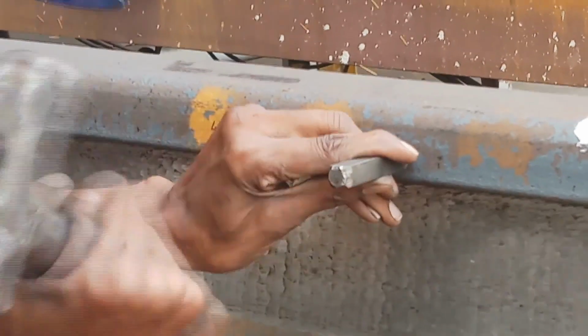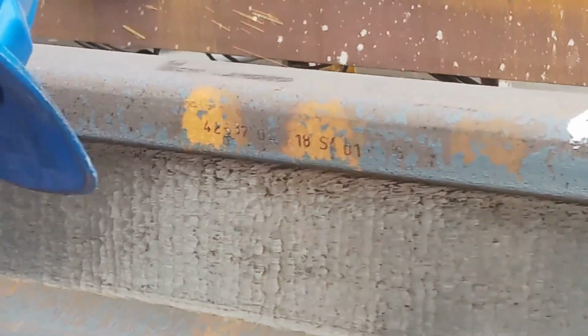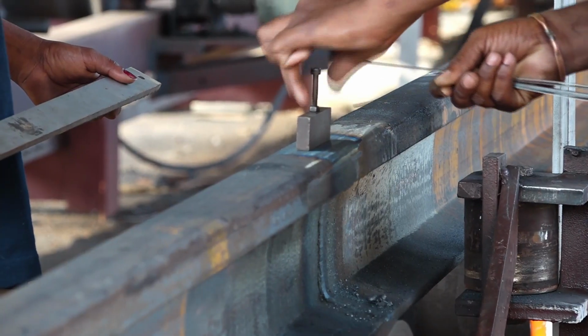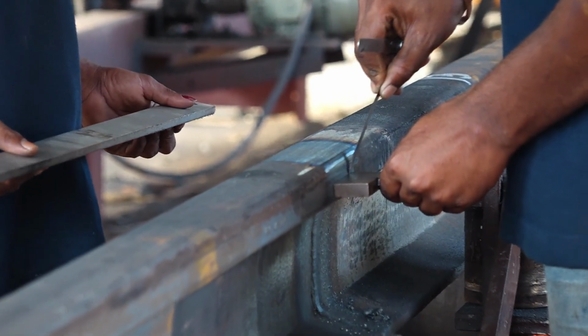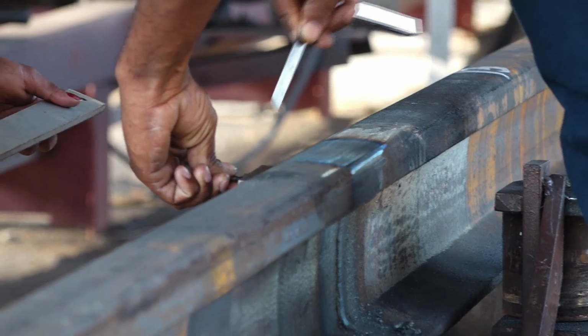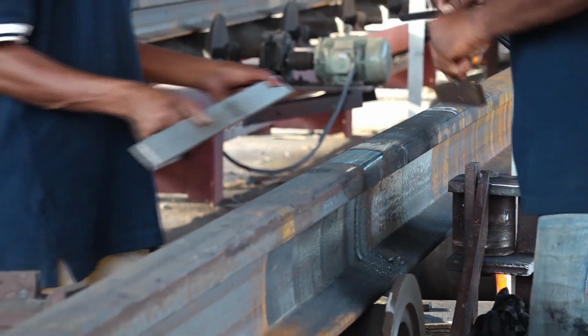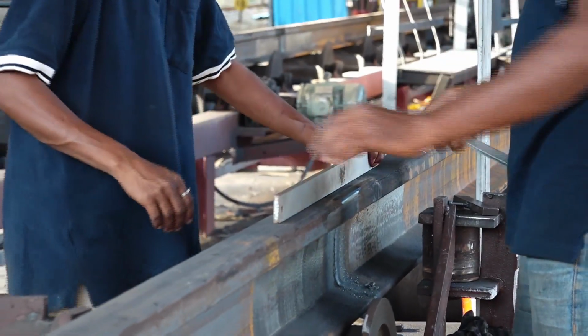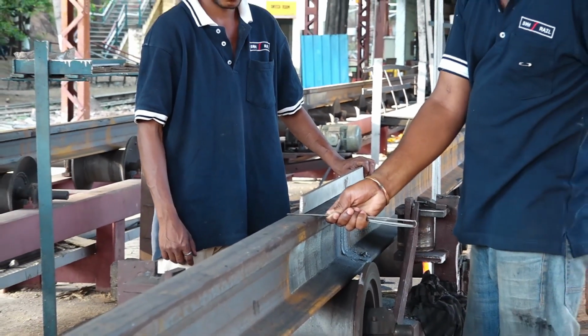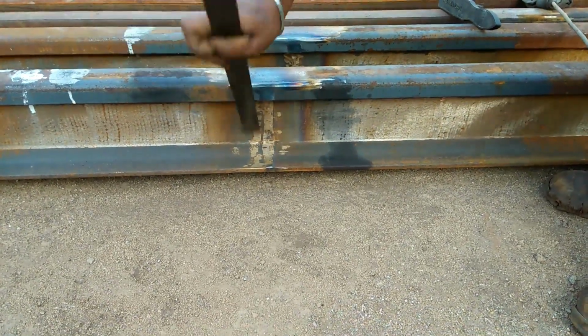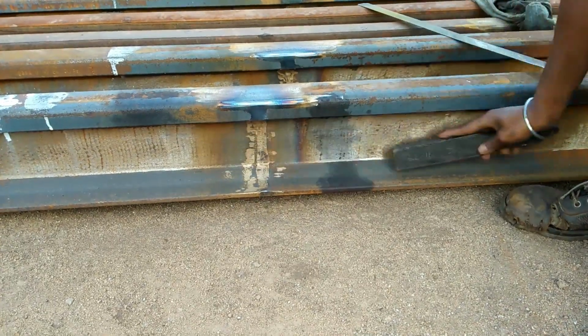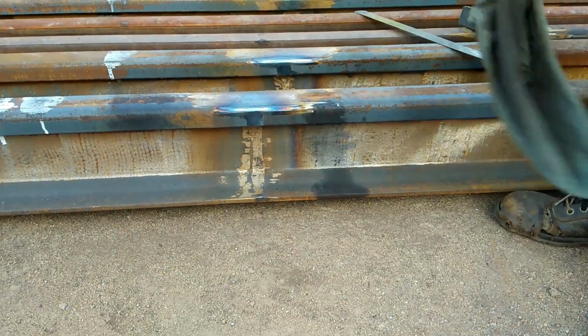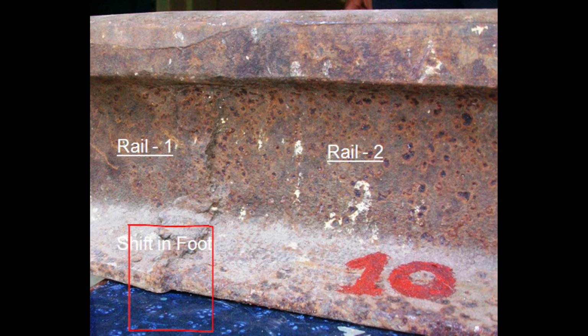Here, dimensional tests are carried out in two places. Number one, after completion of profile grinding, with a standard 1 meter straight edge and 10 centimeter scale with feeler gauge. Then on stacks also. Then afterwards, cleaning of welds for inspection, particularly visual inspection, because in visual inspection there is the possibility of cracks, foot shift, mismatching of rail head and other surface defects like notching and damage in the heat affected zone, etc.